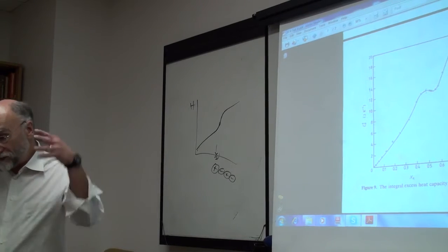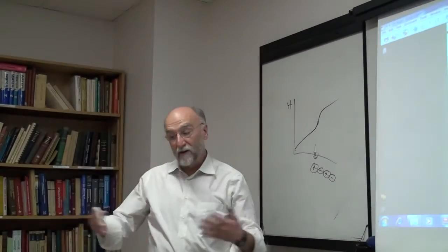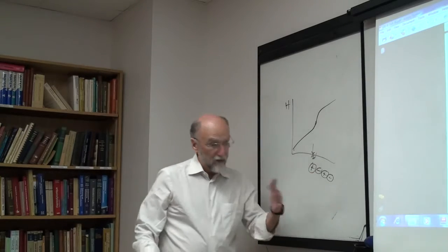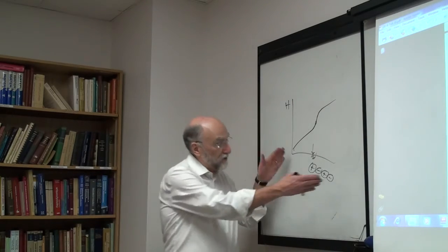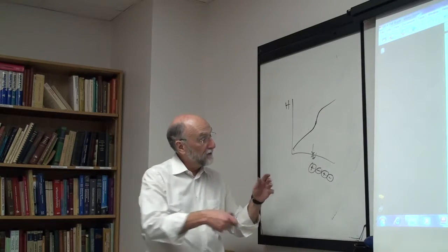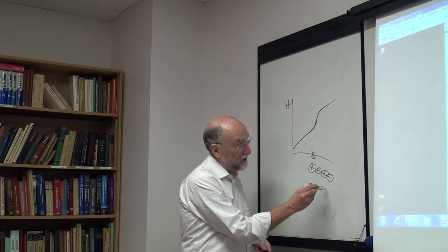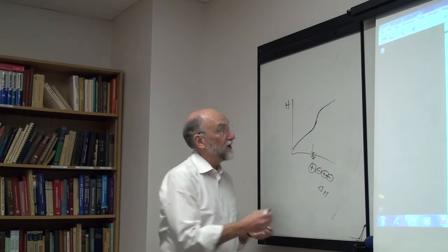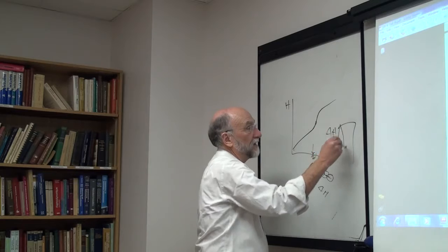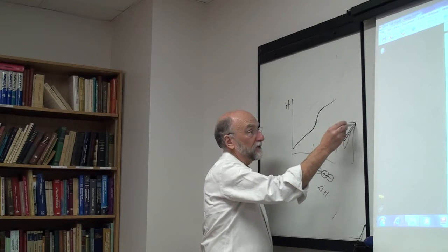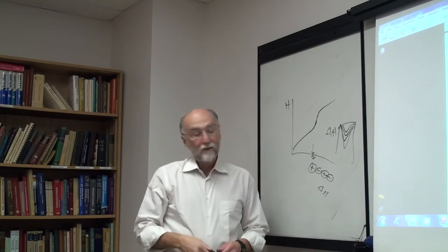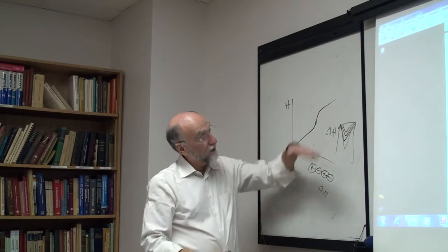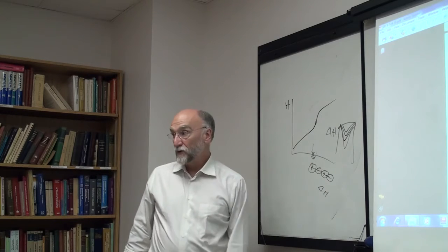Because the entropy becomes more important. As you go to very high temperature, everything becomes ideal. So the ordering decreases as you go to higher temperature. And of course you have ordering because you have a negative heat. The energy of forming these bonds, the delta H, is negative to form the bonds. The heat of mixing is negative like this, but as you increase the temperature, the heat of mixing becomes less negative. Because you have fewer AB bonds, less ordering, so you don't get as much negative enthalpy, so you absorb heat.